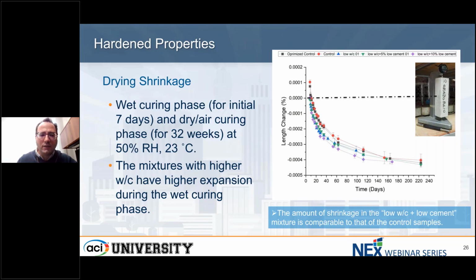So at the beginning, the initial wet stage, obviously the control system had more expansion, and we know that is because of the higher cement content. And when we look at the drying shrinkage data, we see pretty comparable data between our optimized low cement mix design and the control one. Even if we subtract the impact from that initial expansion, they perform maybe a little better than our control one. So overall, the shrinkage performance is comparable for the developed sustainable mixes compared to the control one.